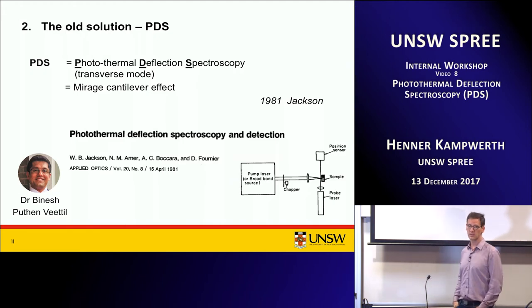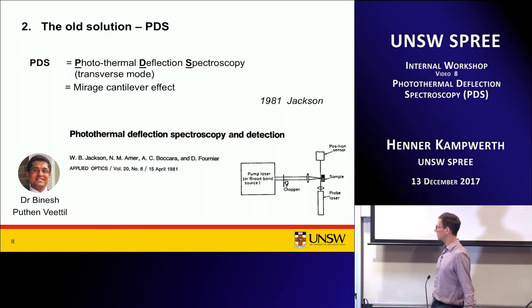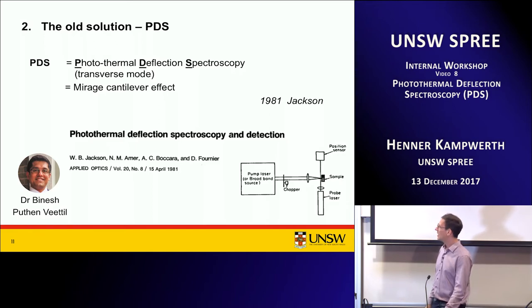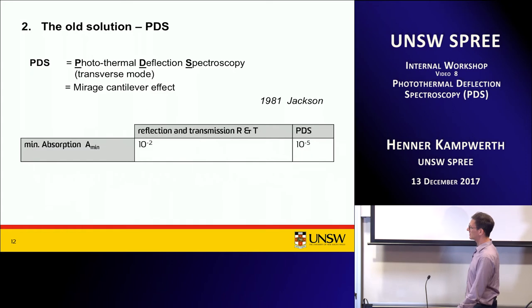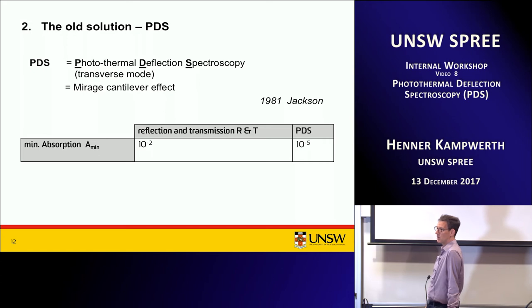PDS is an old technique — it was proposed in 1981 by Jackson in a very nice paper that laid out the entire theory, limits, and everything. Binesh said fantastic, we'll build it here at the university. It took him actually two and a half years before it was operational — much longer than anticipated. The advantage of PDS is the minimum absorption it can measure: R&T is about 1%, but PDS is a thousand times more sensitive — incredibly sensitive — and it should be very good on thin films.